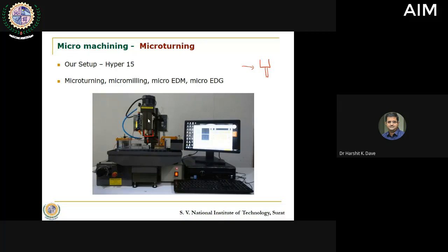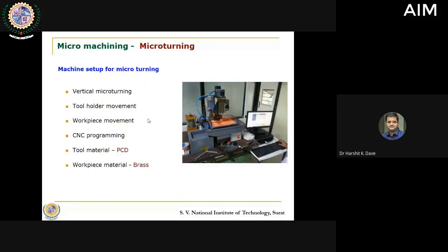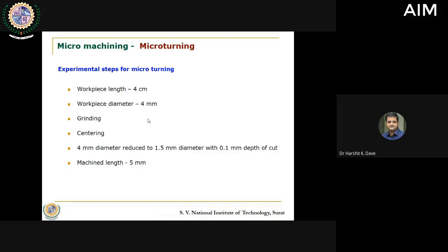Instead of conventional lathe machines, in this particular setup you have the workpiece rotating on a vertical axis. You also need to take care of the tool holder movement and the workpiece movement with the help of proper CNC machining. We used a PCD based micro tool, and brass was used to create the micro shafts. The workpiece we used was brass of 4 centimeter length, and the diameter was 4 mm. We carried out proper grinding of these edges, and we also carried out proper centering of this part when it was put up on a vertical axis.